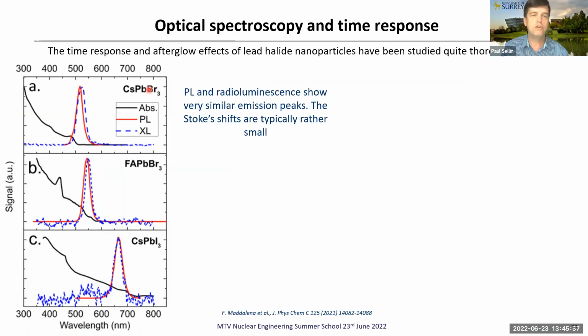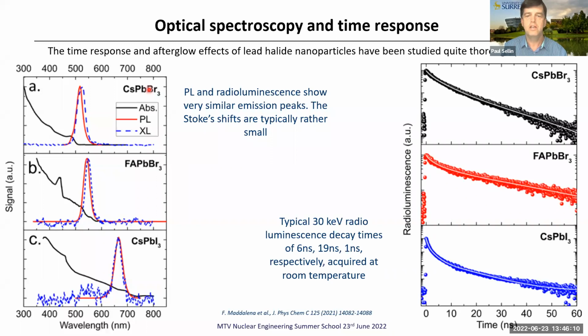First studies have shown that the photoluminescence, for example, follows the expected trend. Photoluminescence from cesium lead bromide and cesium lead iodide. The decay time, actually in this case X-ray radioluminescence using a pulsed X-ray source, showing long decay times, which indicates long-lived excitons within the material.